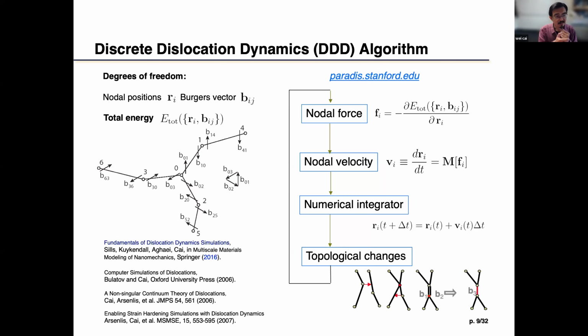Now this is just a very, very brief overview of what the discrete dislocation dynamics simulation is. So we try to model the discrete dislocations. They form a network. How does that network evolve during plasticity? The way we do it is that you discretize the network by segments. So the segments are described by the nodes, and they carry the Burgers vectors, and then you do this computational loop. So at every cycle, you calculate the force. That's mostly based on elasticity.